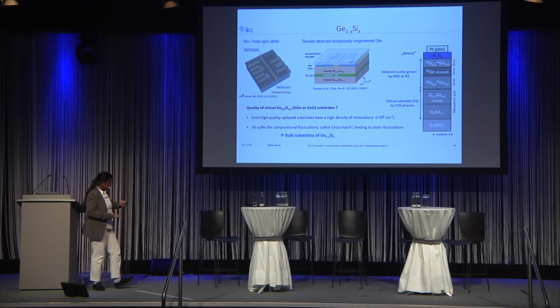So one of the possible options is to go for bulk substrates of germanium silicon to replace this virtual substrate. The bulk crystals, most of the time, have very low dislocation density. It is 3 or 4 orders lower than the epitaxial layers. So if we replace these virtual substrates by bulk silicon germanium, then we can get very good device structures with very high efficiency.